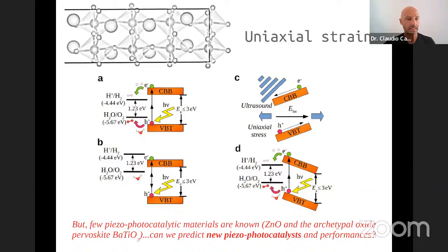So this looks like very interesting properties, but as a matter of fact, piezo-photocatalytic materials have been very, very scarcely explored in the field of catalysis. The archetypal piezo-photocatalytic materials that have been reported in the literature are zinc oxide and barium titanate, of course. Barium titanate is an archetypal piezoelectric material, an oxide perovskite that is very well known and very stable. It's very cheap, so it's a very nice material for all these applications.